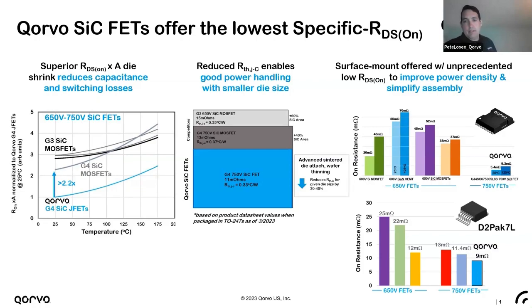The drift mobility, the bulk mobility, decreases with temperature. And so if you come off of that steepness, it essentially means there's some other parasitic resistance in the device that's not following that bulk mobility decrease. And so what you see is that MOSFET evolution from Gen 3 to Gen 4 is actually steepening that TEMCO. And that just means that they're getting better and getting closer to the ideal conduction characteristics that the silicon carbide JFETs already have. So while the temperature dependence is steeper, it's still a sizable advantage across the whole useful operation space.